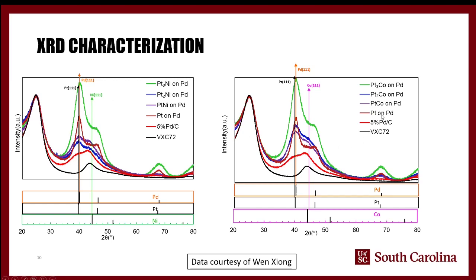Similarly with cobalt, nowhere in here do you see a cobalt peak. So again, it tells us that we're forming this majority platinum, which is why we see a platinum peak. And then of course we had the palladium peak sort of in the background as well, but there's no cobalt peak. So there's no monometallic cobalt forming. So all the cobalt that's depositing is depositing with the platinum and forming some kind of a bimetallic alloy.